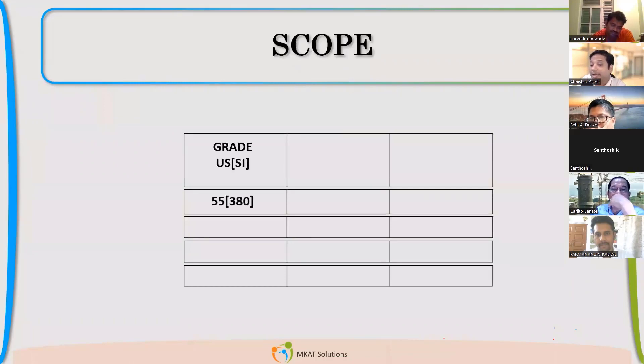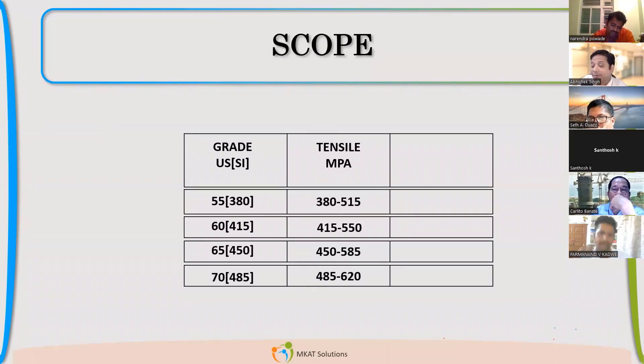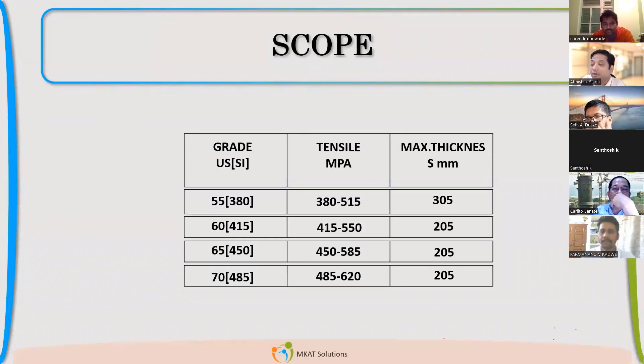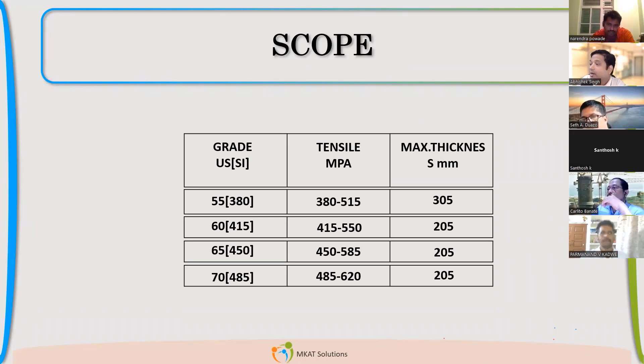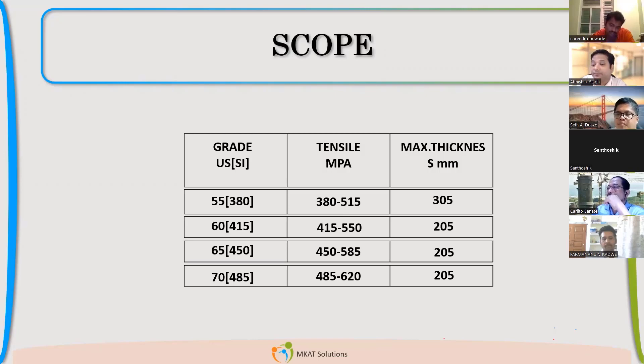In the scope, the material is divided into four grades, and the tensile properties are briefly given. There is also a limitation on thickness based on grade. For example, I cannot find a 300 mm thick plate for Grade 70 because it is not produced. The maximum thickness available for SA 516 Grade 70 is 205 mm — beyond 205 mm, you won't get that grade.